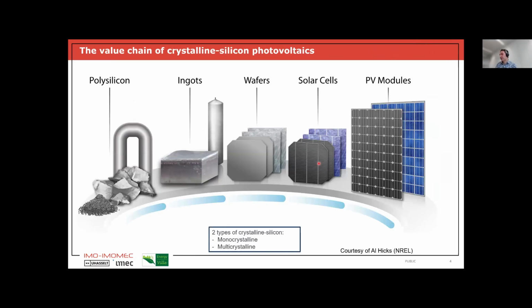So in this talk, I will focus on crystalline silicon photovoltaics, and you can roughly distinguish in the value chain going from sand to a PV panel based on crystalline silicon 5 different steps. First, we have to make very pure polysilicon, starting from quartz or sand. Then this polysilicon is molten and a very large ingot is produced. The ingot is then wire sawn into individual wafers. The individual wafers are processed into individual solar cells. And then the solar cells are interconnected and encapsulated in the PV module.